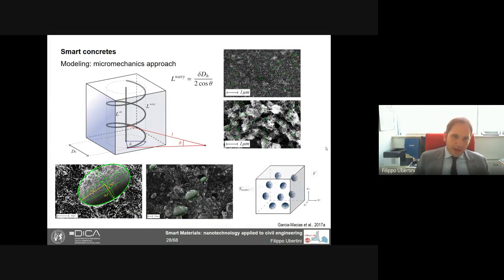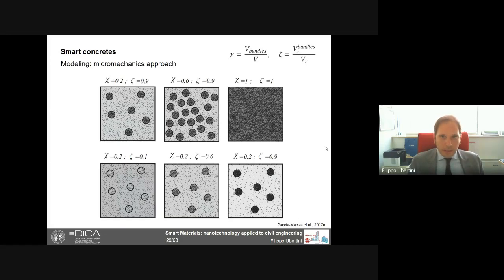What we've also introduced in this framework was considering the evidence that we have from our experiments. So the nanotubes are not straight, they're sort of twisted, they're sort of bended. So we introduced these wavy nanotubes, and also, whatever the efforts we make to distribute nanotubes in a uniform way in the composite, still we will have agglomerations, still we will have bundles. We will have these sort of ellipsoids in the matrix, and we have to consider those. So we have considered those agglomerations through the factors chi and zeta that are related to the relative volume of the bundles with respect to the total volume, and the relative amount of agglomerated nanotubes with respect to the whole nanotubes.